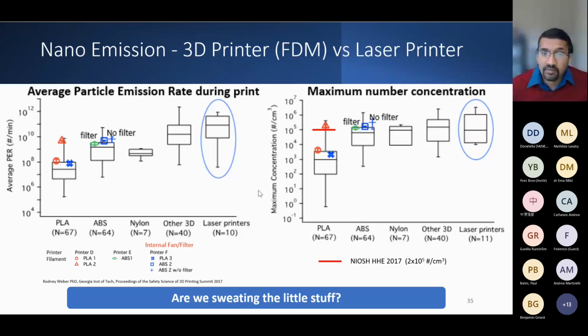And the study by Rodney Weber, which was done at the 3D Printing Summit in 2017, actually summarizes that in a very effective way, kind of talks to particle emission rate during printing of a standard part. And if you can look across using multiple materials and a good sample size, they compared the average emission rate during print with 3D printing material PLA, ABS compared to laser printers. And you can see the emission rate is not distinct or different. And one could argue, for the most part, lower than what you see from laser printers, right?